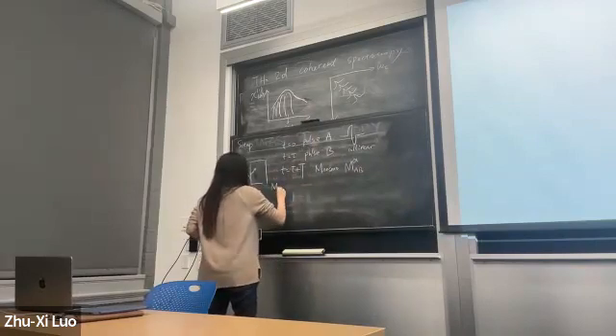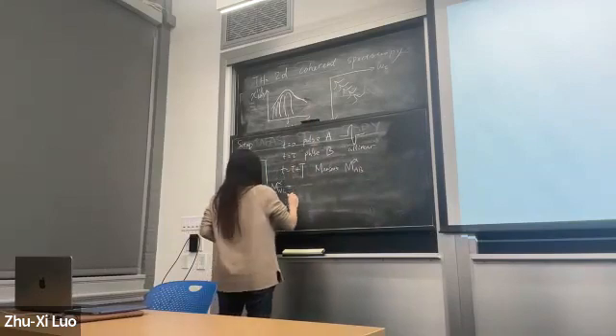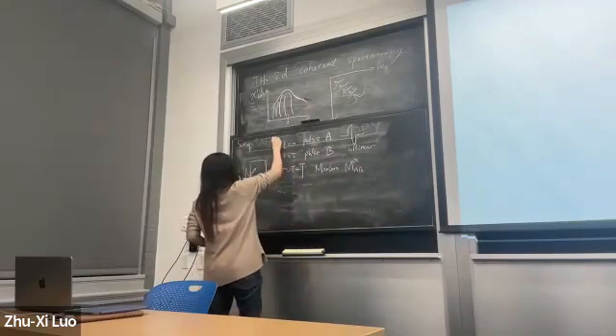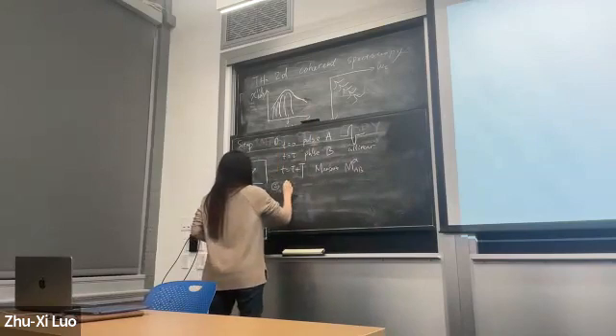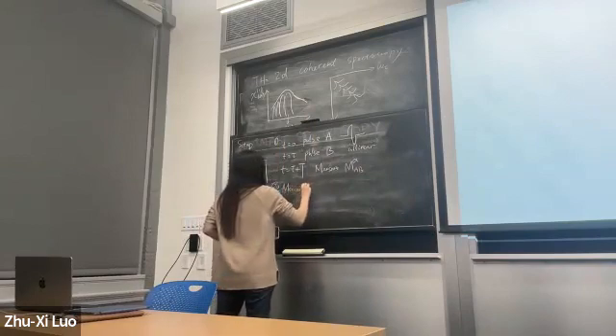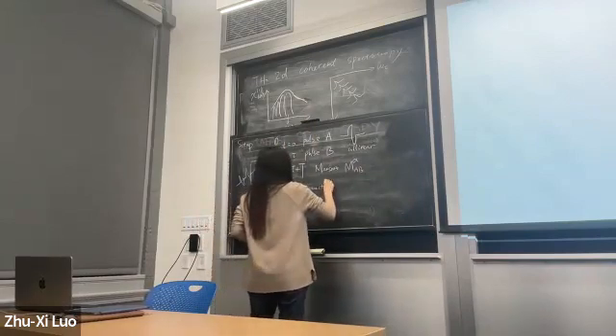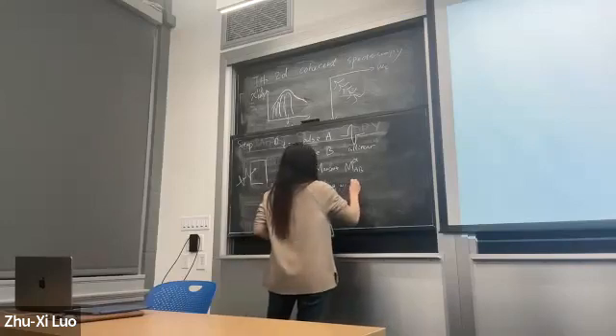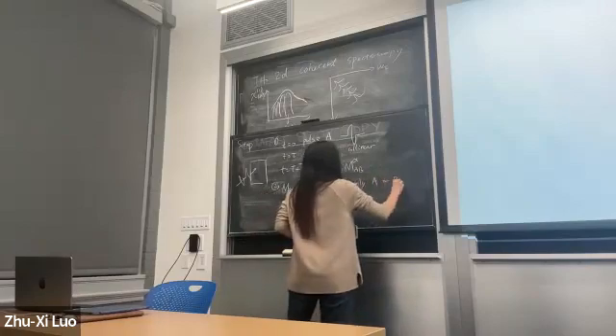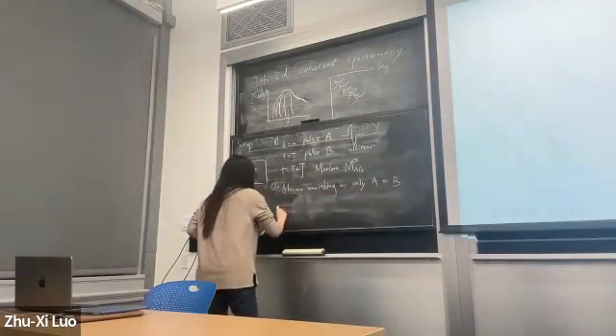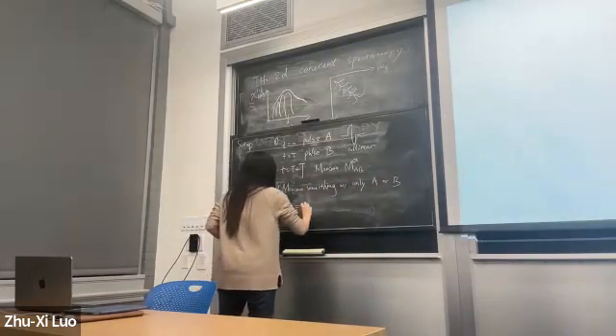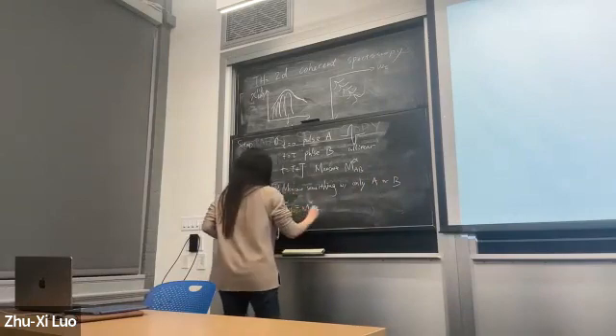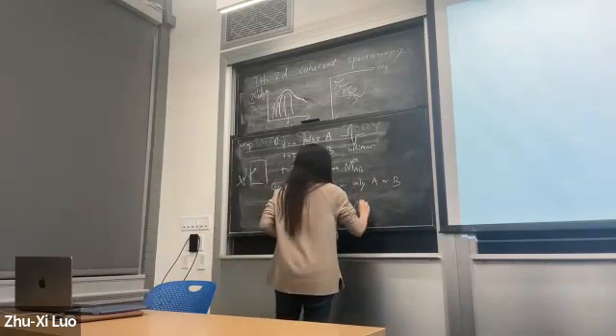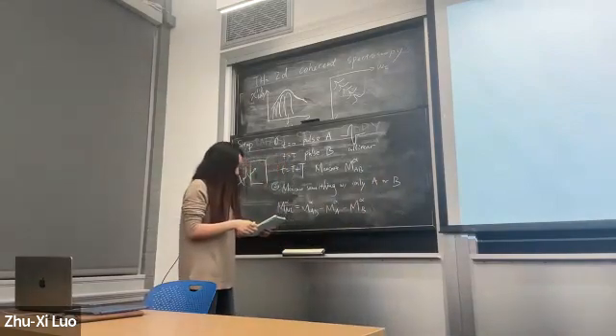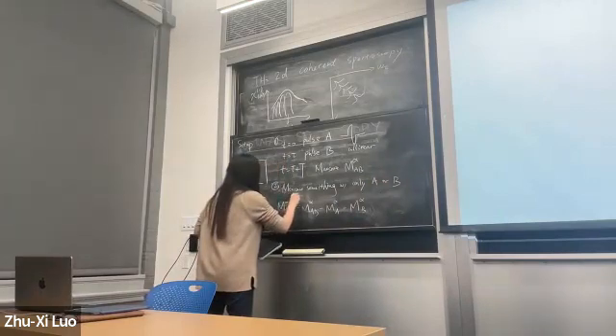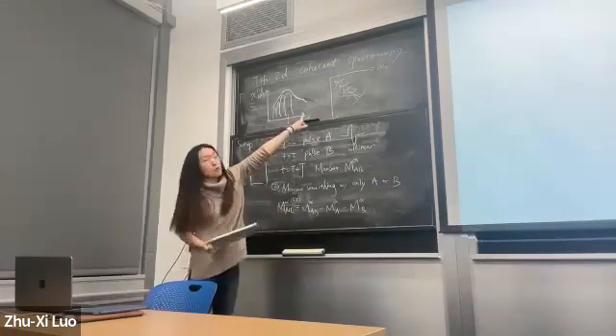And so this is the first cycle of the experiment. For the second, you measure the same thing with only one of the two pulses, A or B. And then the nonlinear response of the system would be M alpha AB minus M alpha A minus M alpha B. Right, and then you do a Fourier transform. So this thing will be dependent on both tau and t. You do a Fourier transform, you get a two-dimensional frequency diagram.